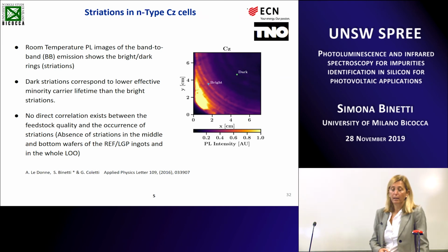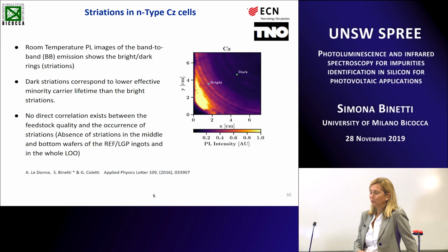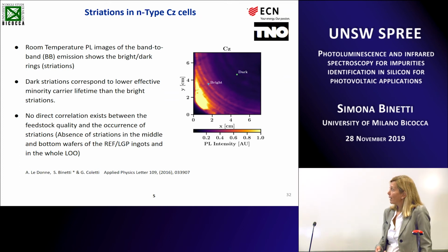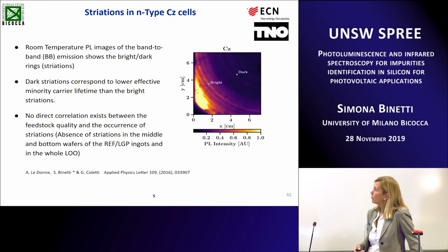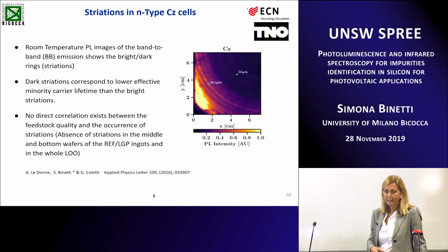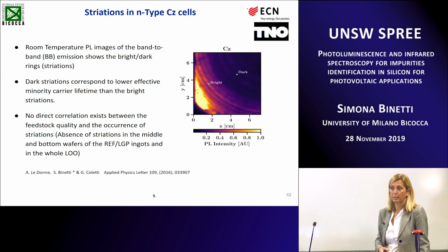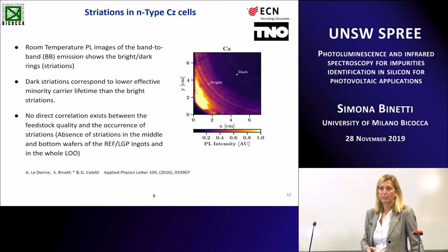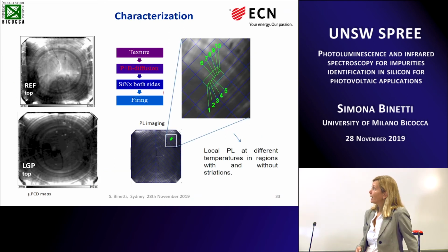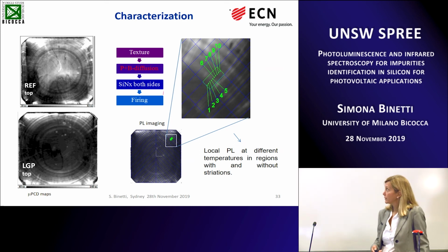Performing photoluminescence mapping and microphotoconductivity mapping, we have seen the famous striation related to the agglomeration of point defects, but we have seen also that there was no correlation between the type of ingot or impurities in the ingot and the presence of striation. But what we have observed is that in the low oxygen content ingot, there was no evidence of striation. So we thought about the presence of oxygen precipitates in these cells, and so we cut several pieces of wafers in a region with and without striation to perform local microphotoluminescence on these samples.